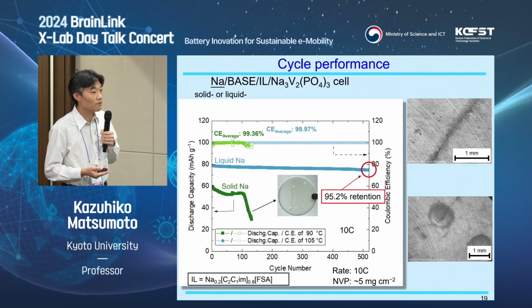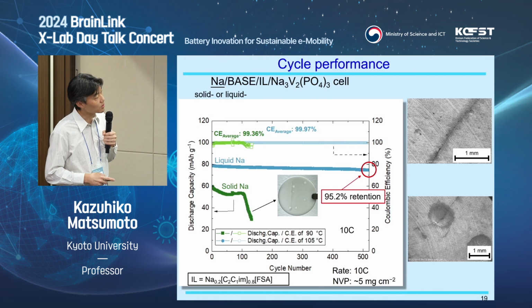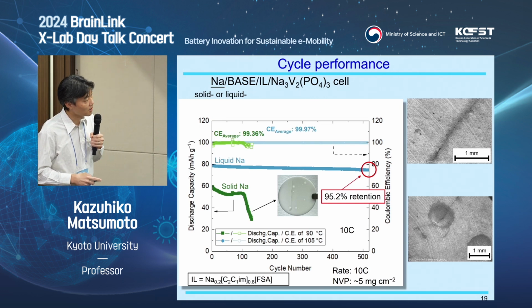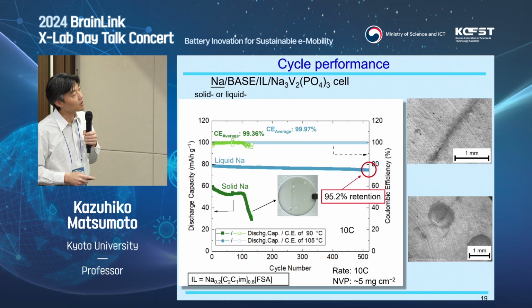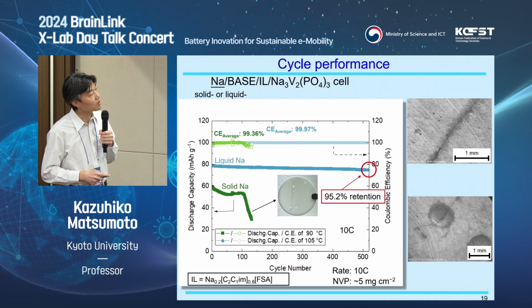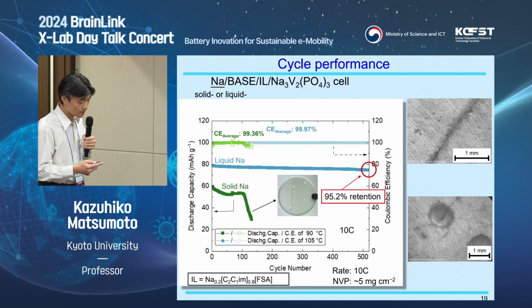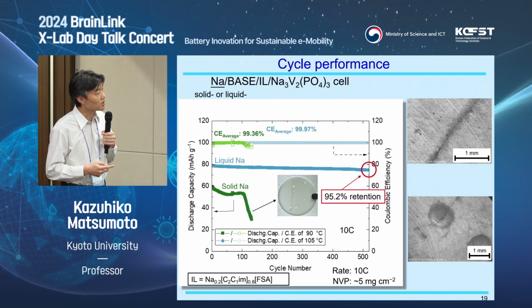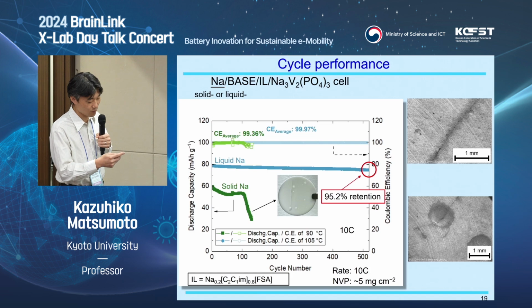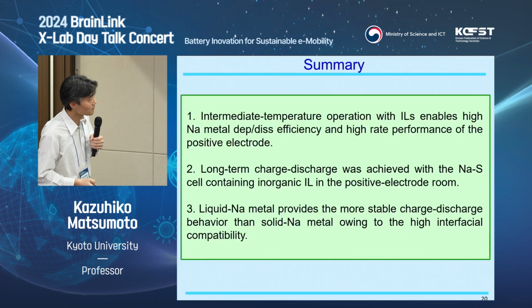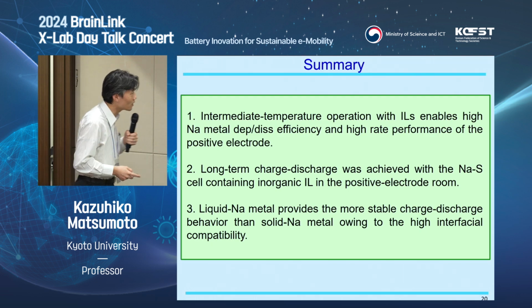Here, even visually, we can confirm the damages, and by microscopic observation, we saw a crack or even some holes. Seems to be a very harsh reaction occurs on the beta alumina with the solid sodium metal. So when we work with solid metal, we obviously have to be very careful even if we use a solid state electrolyte. So this is a summary of my talk.